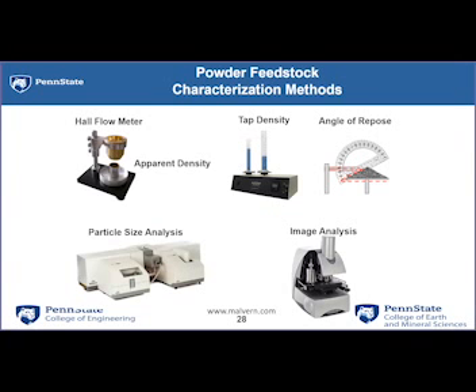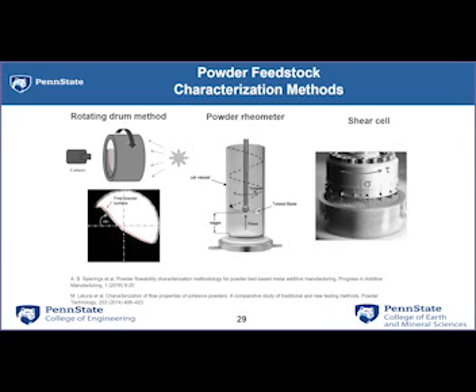We have the typical characterization techniques, and we go through those. But in powder rheology, what we're really trying to understand is how powders behave a little bit more like fluids at larger scales, and looking at tests that are more indicative of what a powder might be going through, especially in the additive manufacturing field, where we're spreading a powder with a blade, or running powders through nozzles and feeding them into molten liquid pools to build up parts.